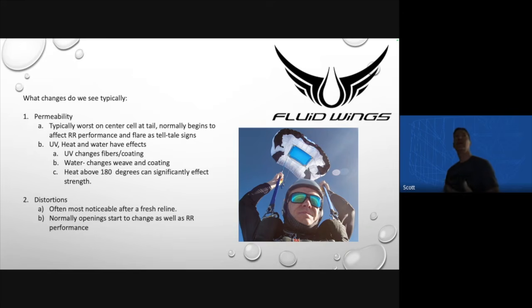So you can't watch it, but you can see that permeability starts to increase. Typically what we see is rear riser performance drops when the permeability goes up, and the flare tends to drop, right? Heat does have effect on it. Anything above 180 degrees really does affect the strength of nylon. Water changes can affect the weave coating. So when you get a parachute wet, has anybody got a 0 to 3 or an F111 type parachute wet before? Notice some changes. So that change primarily is a calendaring change, right? Because you don't have coatings. When you get fabric wet, you can uncalendar.